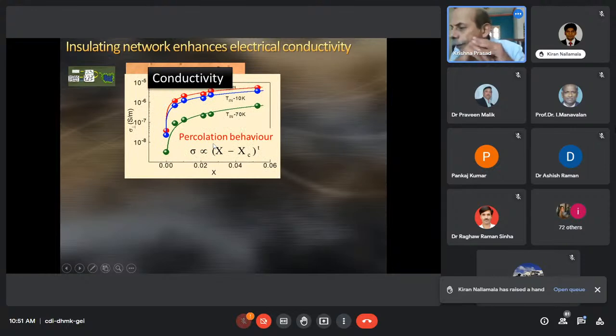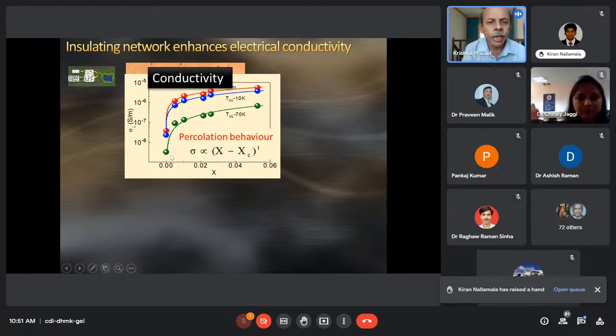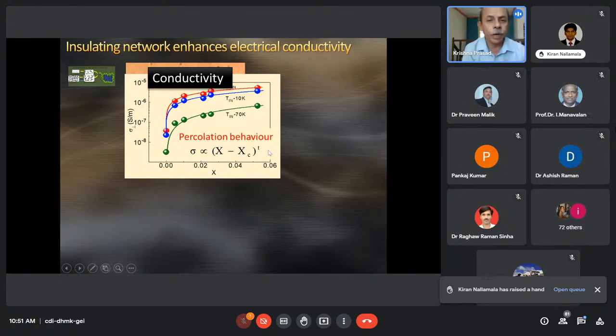If you measure the conductivity of such a system, they show a percolation behavior, which means that at very low concentrations, for example, the conductivity is that of a true insulator, which a liquid crystal is. Liquid crystals by design are made to be insulators because of the display industry especially. But when you go on adding gold nanoparticles, the conductivity could pick up by a few orders of magnitude in a very sharp rising curve. The magnitude of the conductivity increases, which can be described by a power law, which is a very standard description for a percolation behavior.